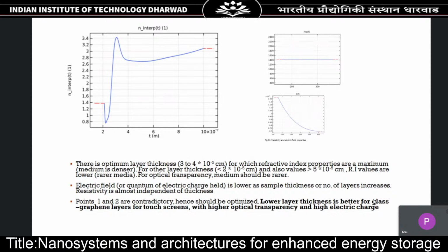And we have done some modeling primarily on the optical properties. So the left-hand side shows the refractive index behavior versus thickness, and the right-hand side graph shows the electrical behavior with respect to thickness. So what we have found is there is an optimum layer thickness for which the refractive index or properties are a maximum. And for other layer thicknesses, the refractive index values are lower. But what we require for optical transparency is that the medium should have lower refractive index. And similar trends were observed for electric field. So what we have found is electric field is lower as the sample thickness or number of layers increases.